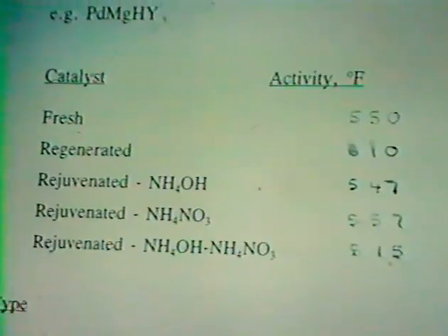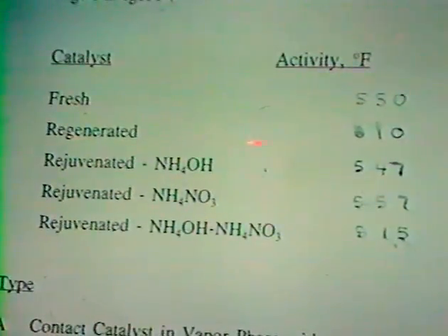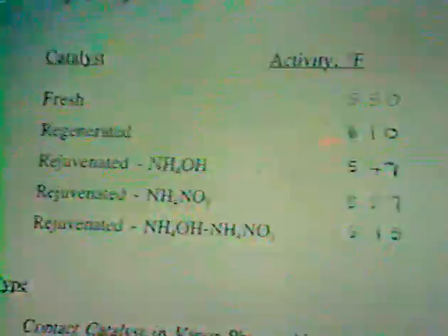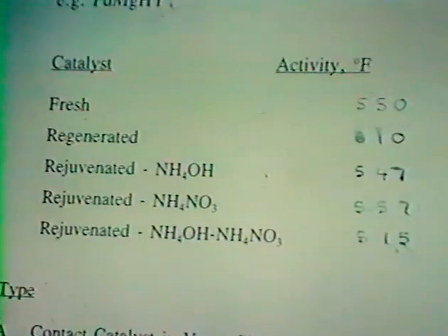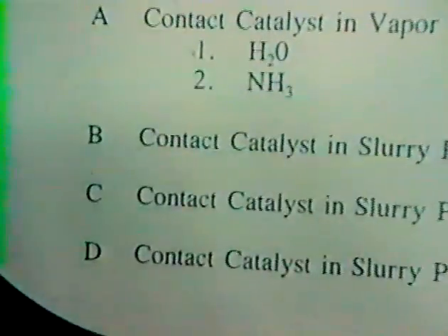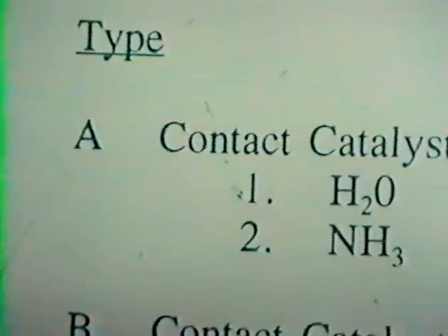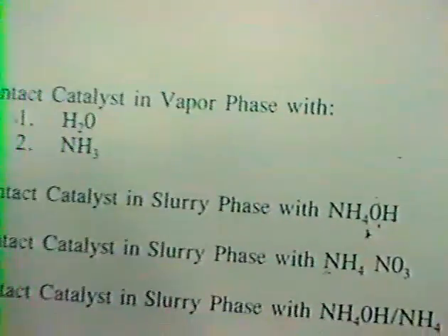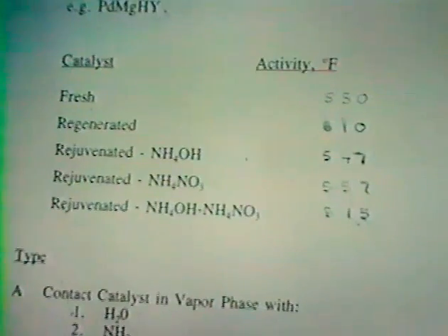We treat that catalyst then with ammonia gas, which has been preceded by water, or with aqueous ammonium hydroxide. We can restore the activity to essentially the fresh catalyst activity. If we treat it with ammonium nitrate, we can restore the activity within 10 degrees of the fresh catalyst. And if we treat it with a mixture either simultaneously or sequentially with ammonium hydroxide and ammonium nitrate, we actually improve the catalyst activity. Here we think we know a little bit what's happening.